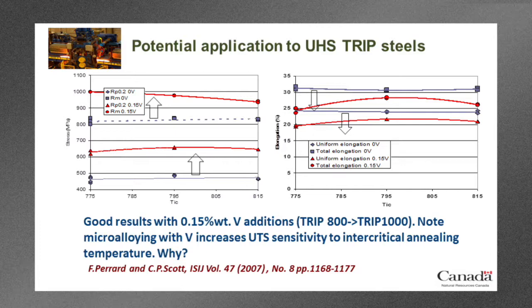On the right-hand diagram, we're looking at the change in the ductility that's associated with that. The blue curves again are the reference steel, and the red curves are the steel once we've added the vanadium. You can see that we do lose a little ductility, but it's actually very, very small, and it's not a real problem for the type of applications that these steels would be used for. These are very, very high-strength steels, 1,000 megapascals. If we can get something like 25% of total elongation, or over 20% of uniform elongation, that's a very, very